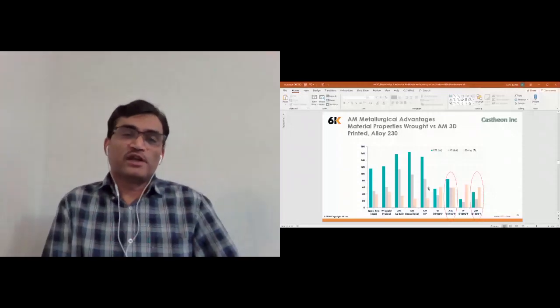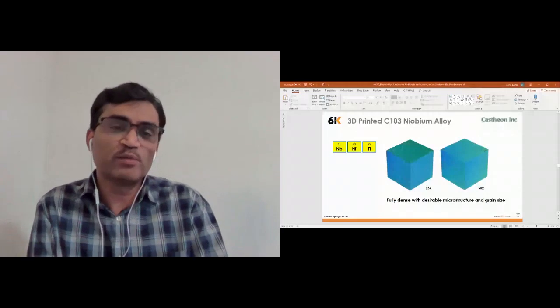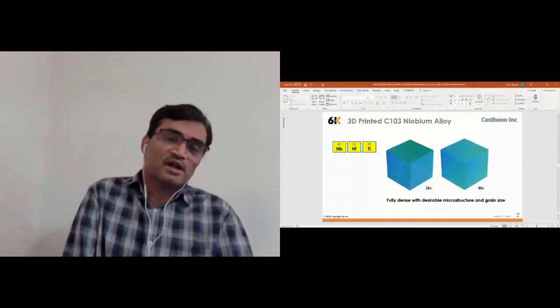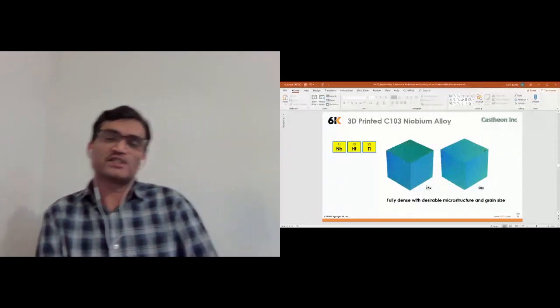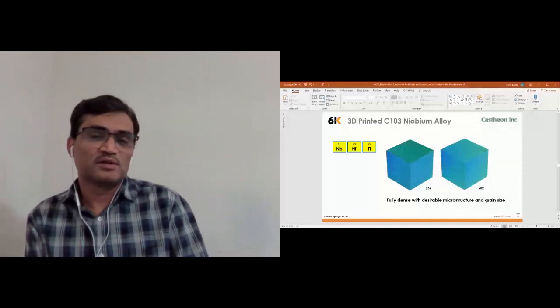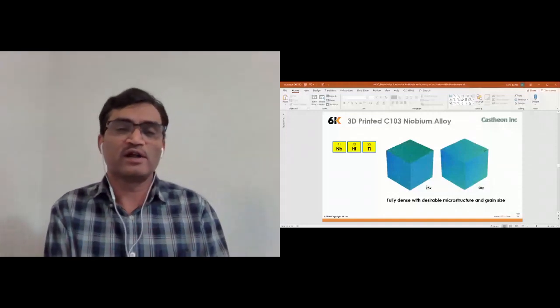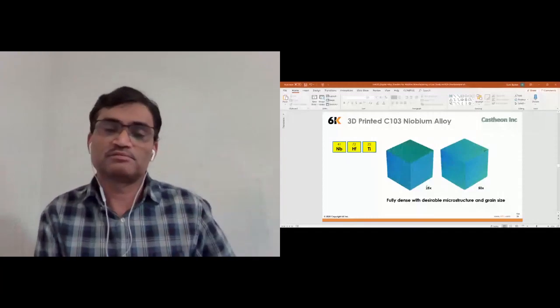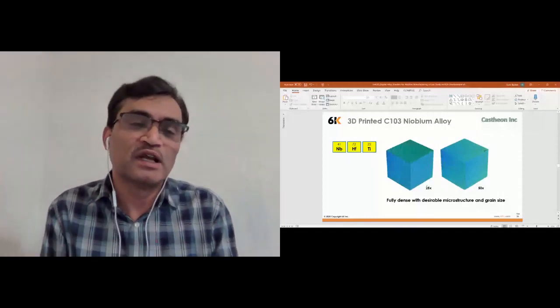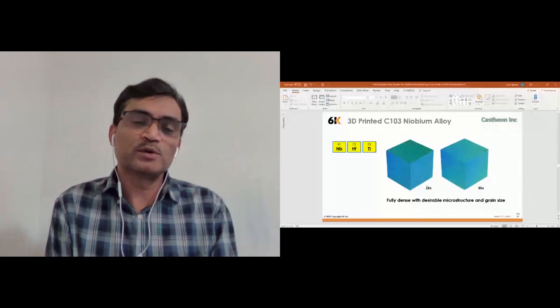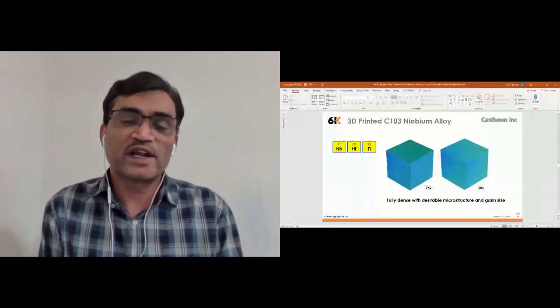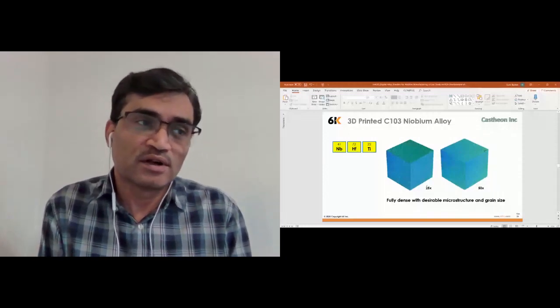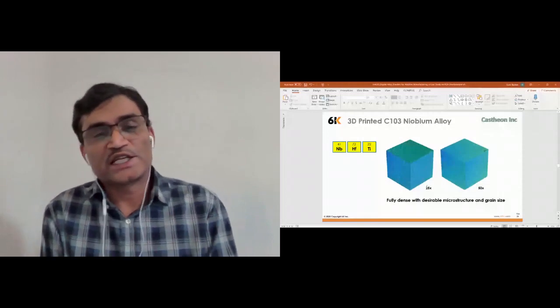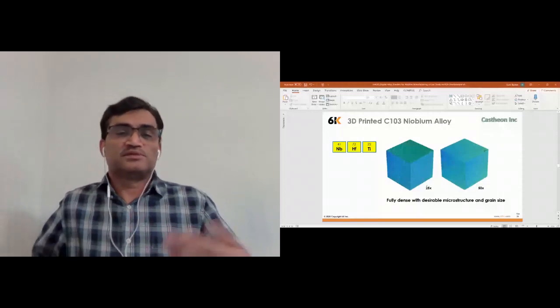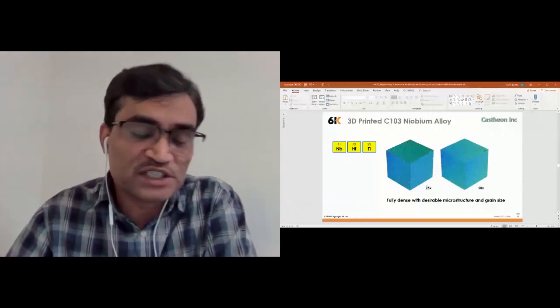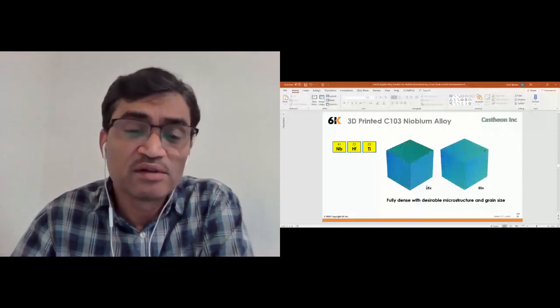And this is again a unique alloy, niobium C103, which is extremely hard to print. It's basically a high refractory alloy, mostly for hypersonic applications, and he is able to produce it with the right combination of parameters and heat treatments. This alloy we can basically print successfully.